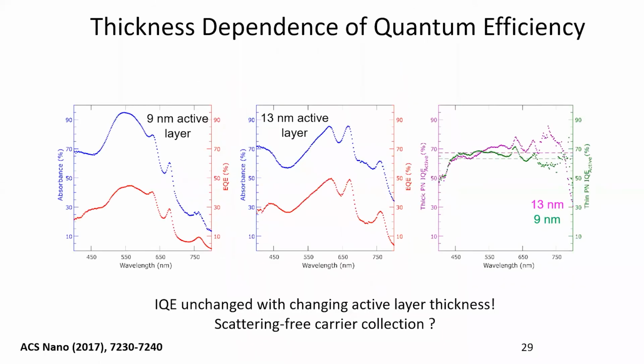We have also observed some more exotic things going on over here. When you are in the very small thickness regime, such as 9 to 13 nanometers, you measure your external quantum efficiency, which looks like very different spectra. But when you normalize them and get the internal quantum efficiency, you see that the internal quantum efficiency is not very sensitive to thickness. And we don't know what is actually happening over here, but we think some kind of ballistic or scattering-free carrier collection is happening, which may be a new transport regime for excited carrier collection. I'll talk a little bit about it towards the end. I would also say that this is still very preliminary, and there is room for more exciting experiments in this area moving forward.